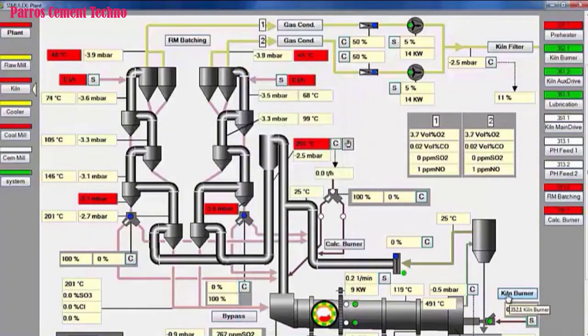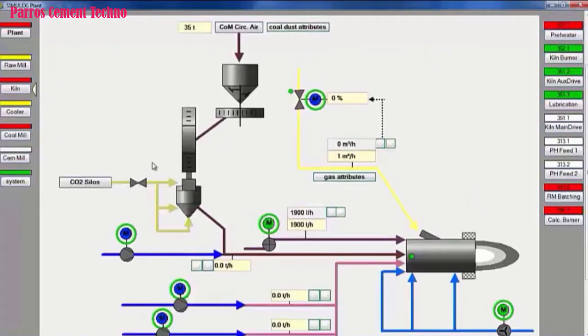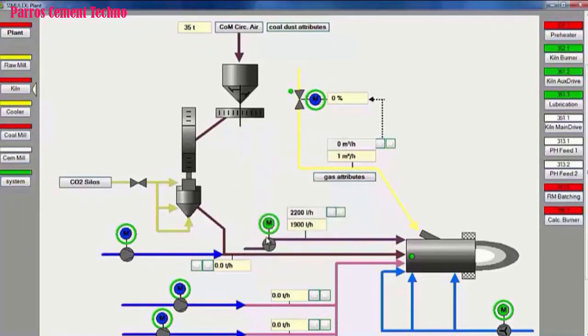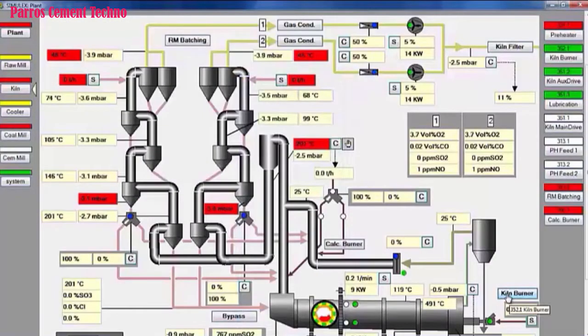Then we increase the use of fuel oil from 1900 liters to 2200 liters per hour. Then at the 6th hour, we will mix fuel oil and coal. The method of mixing with coal is the calorific value of oil, 8,650 kilocalories per kilogram, divided by the calorific value of coal, for example 5,000 kilocalories per kilogram, equal to 1.73, meaning to replace 300 liters of oil with coal, around 519 kilograms of coal.